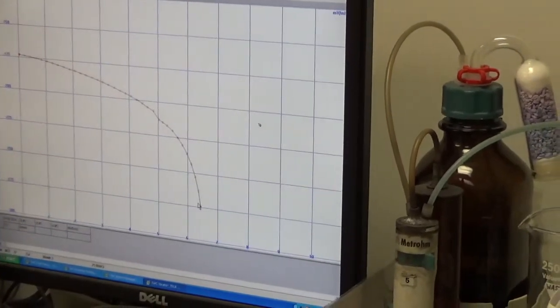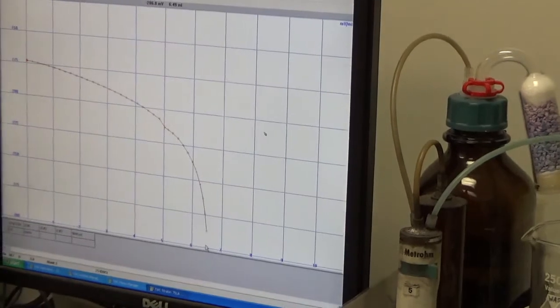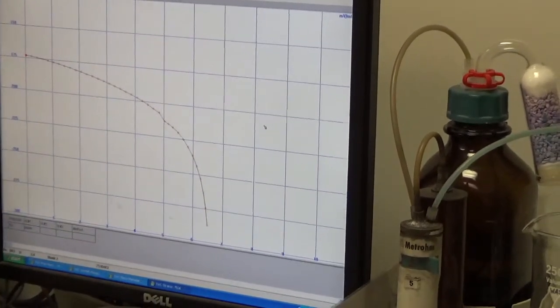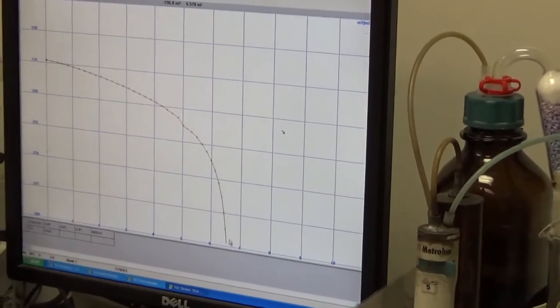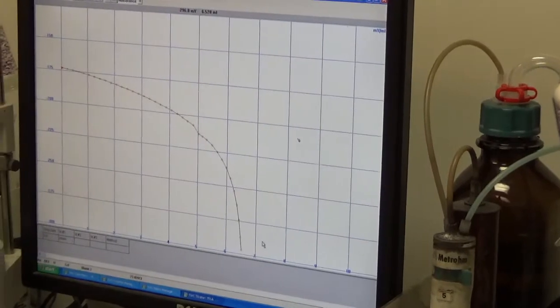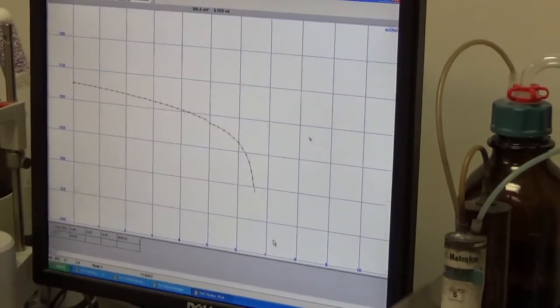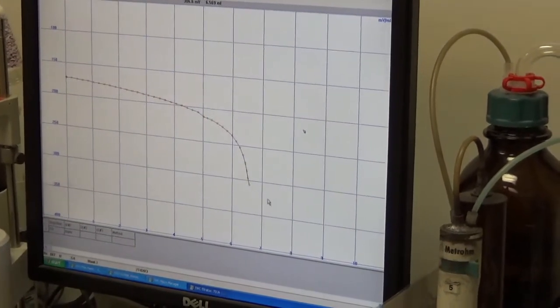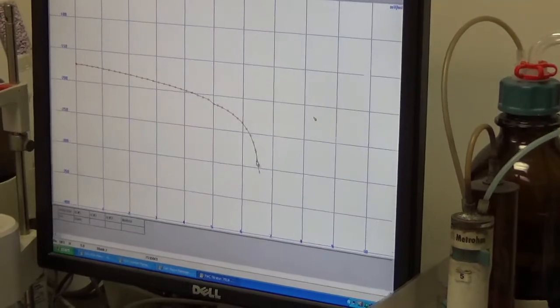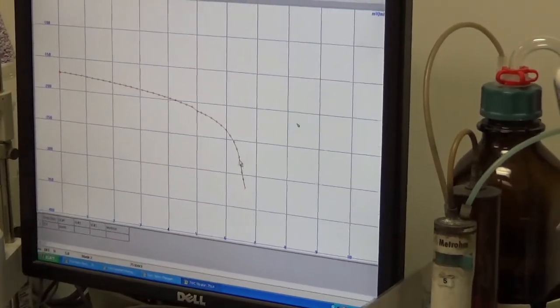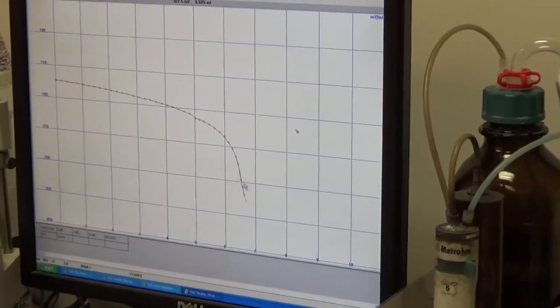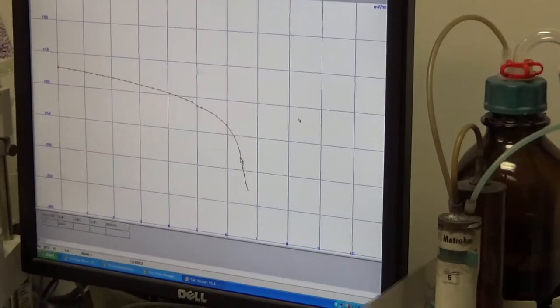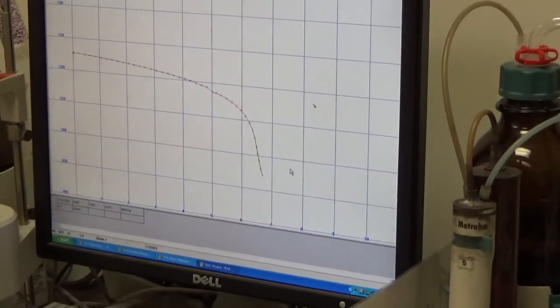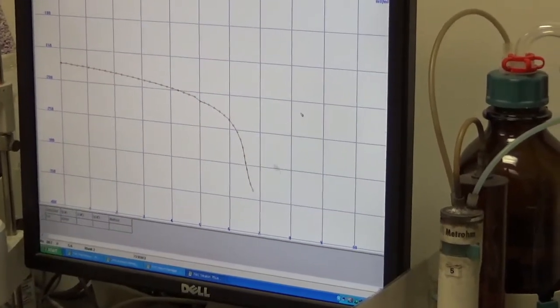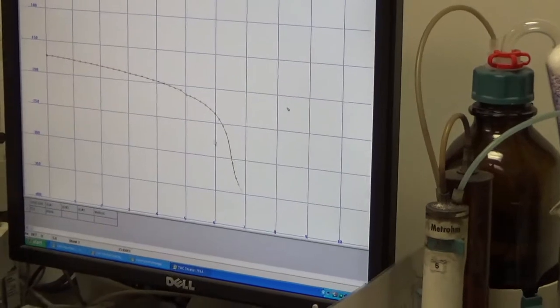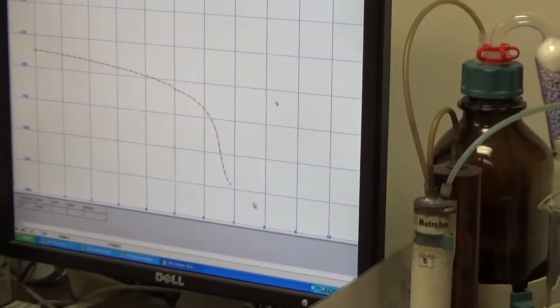As it approaches the equivalence point, every incremental addition of silver nitrate causes a significant drop in the millivolt. So it already passed the equivalence point. It usually passes the equivalence point and then it gives the equivalence point somewhere in this area, the steepest point in the curve. Usually you get an S-shaped curve of titration, whether it's an acid-base or potentiometric titration of chloride.